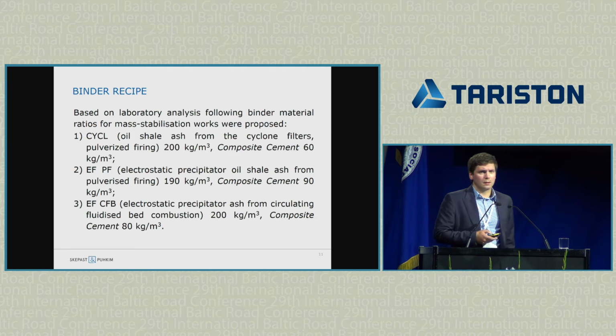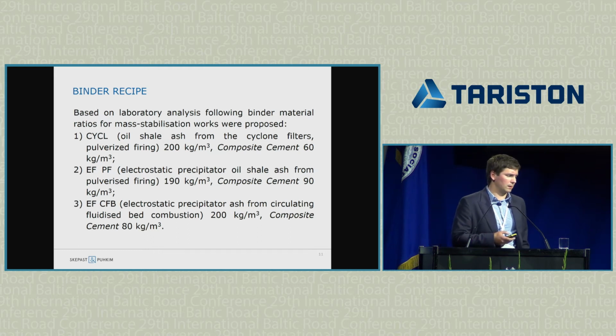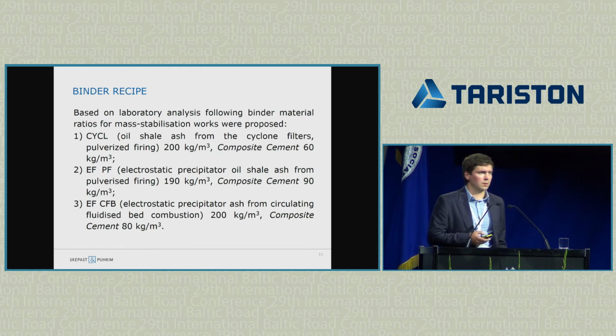And we tried different binder recipes with different oil shale ashes. We tried cyclone ash. We also tried 2 other ashes from the so-called newer burning technology boilers. And we added also some cement to the mixture, because the laboratory results showed that oil shale ash alone does not work so well.